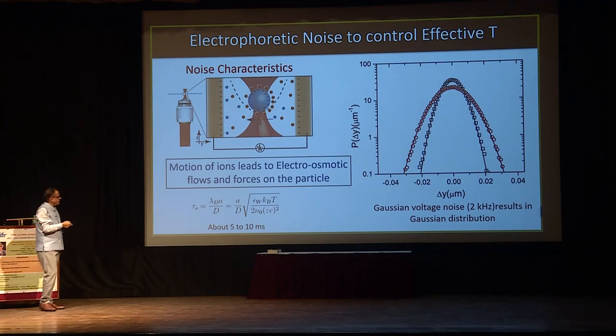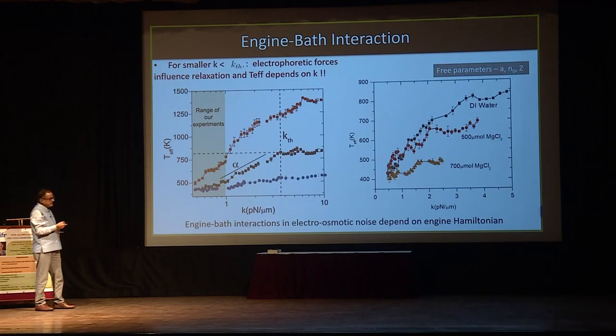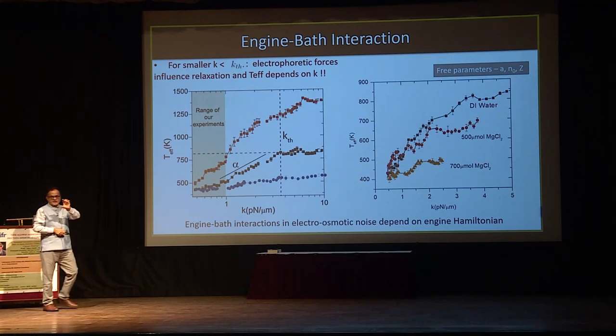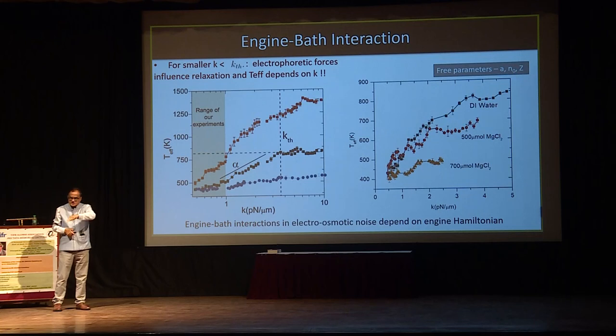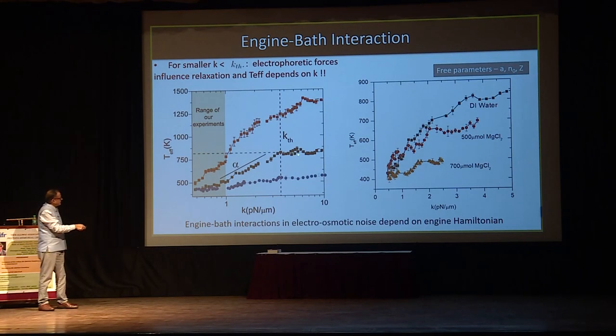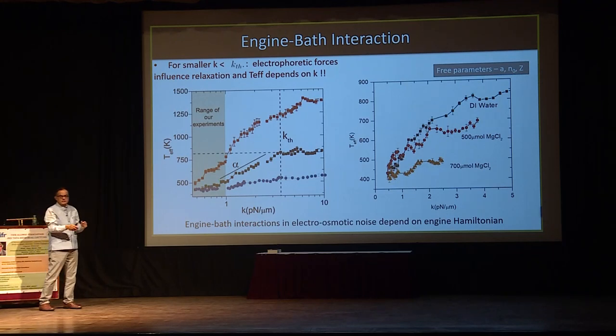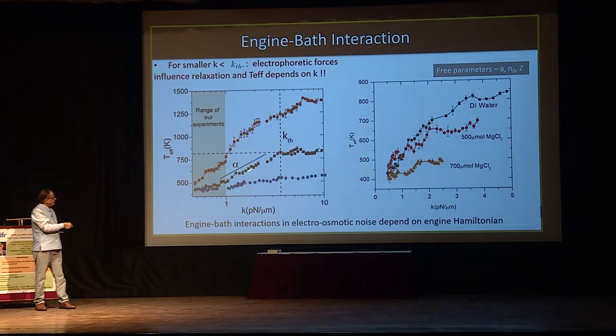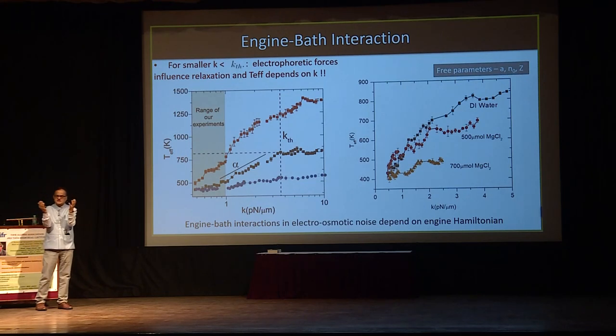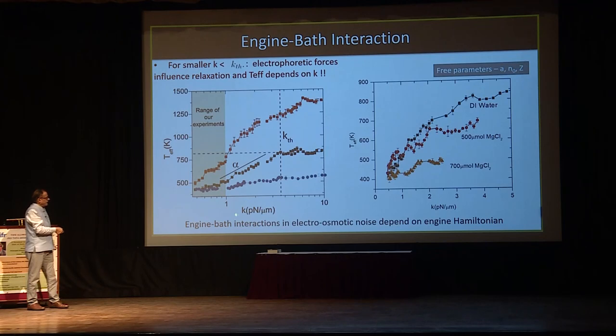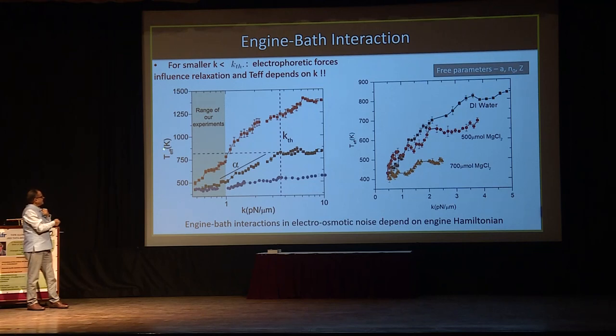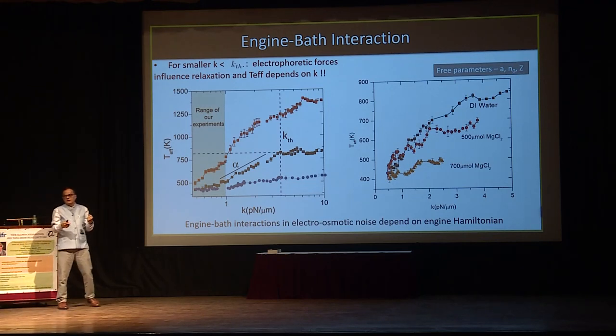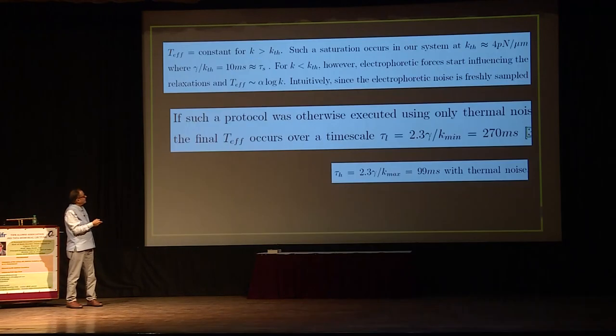And that time scale is now very important in this whole business. So without giving you all the reasoning for it, we showed that for a given fixed voltage, the temperature you will get will not be independent. This is independent if it is a very stiff trap. But if the trap is soft, then the effective temperature depends on the K. This is exactly the system-bath interaction. K decides the Hamiltonian of the system, that is the engine, and T effective is your bath. So here you have a coupling because of electrophoretic noise. Let me give you the detail last.